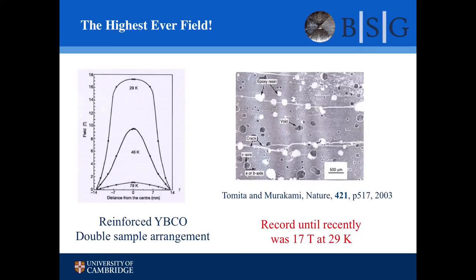So what about record fields? Until recently, the highest field ever was 17 tesla, which is 10 times the field you can generate with iron, 400 times the energy density of something like a fridge magnet, a colossal amount of energy in there, at 29 Kelvin. The sample looked horrible, but that's not the point. Who cares what it looks like if you're generating a field like that? It had a Woods metal down the middle so heat could leak out. It was backfilled with epoxy for secondary reinforcement, and it was even wound ultimately in CFRP to strengthen the material.